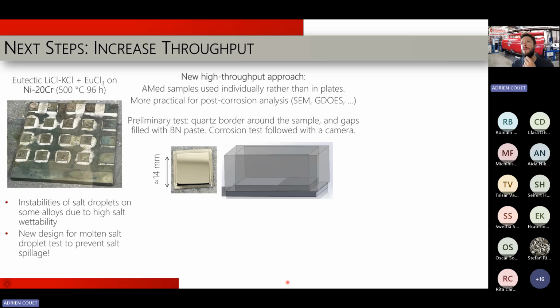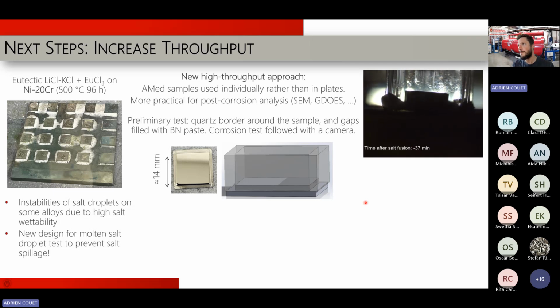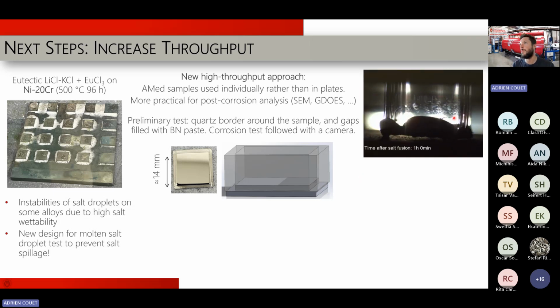So we tested a few things. For instance, we looked at putting some boundaries made of quartz around the sample, and then putting some boron nitride paste to prevent the salt from spilling. Here is an example where you can see one of those droplets melting inside of that quartz with an alloy on the bottom, sorry. And you see the boron nitride paste on the side. It looks pretty good up to a point where it's actually going to leak. Unfortunately, after about 4, 5, 6 hours, we often see that the boron nitride paste deteriorates, and you're losing the salt.